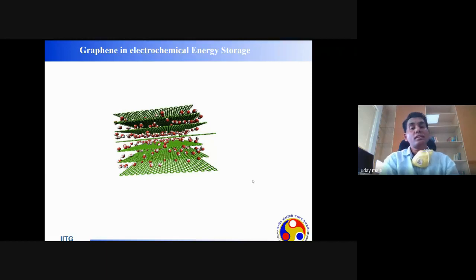But there is a real issue. Because the graphenes are two-dimensional sheets, they have strong interaction to restack back in terms of graphite. People can make the graphene from the graphite, but the graphene again has a tendency to restack to go to the graphite phase. And if they restack, then you cannot access the intermediate layers. You can just access the outer layers only. So how to restrict this restacking problem, which is a huge problem for graphene-based systems in energy storage?